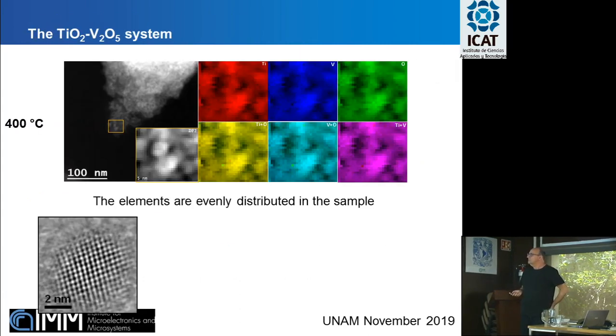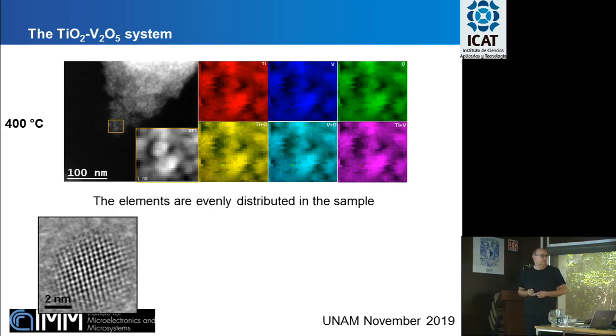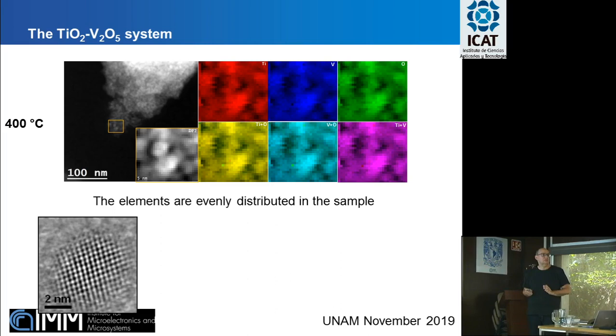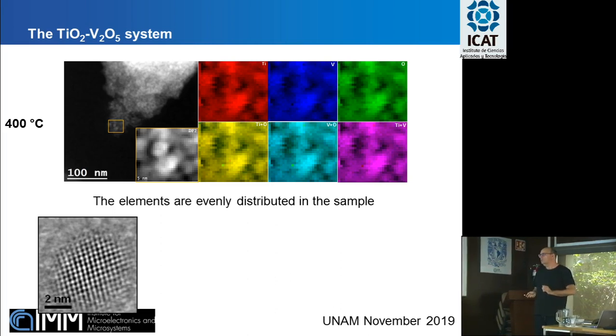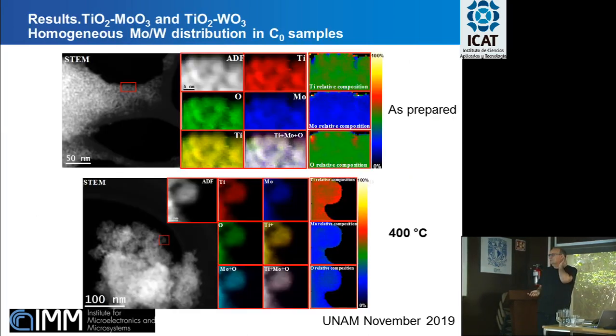This is elemental mapping of the materials, showing that the elements are evenly distributed in the sample. We have carried out this kind of analysis for many, many different samples, and in each case the vanadium distribution was always uniform, which is not always the case. For instance, this is another system, titanium modified with molybdenum oxide, titanium modified with tungsten oxide.